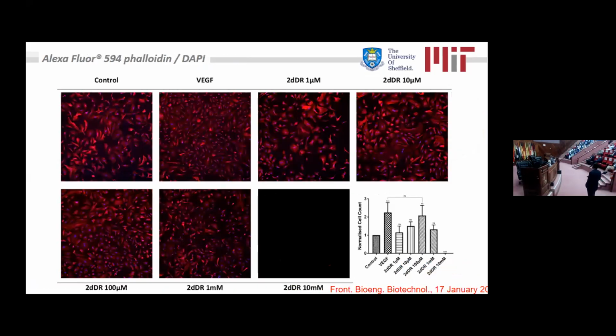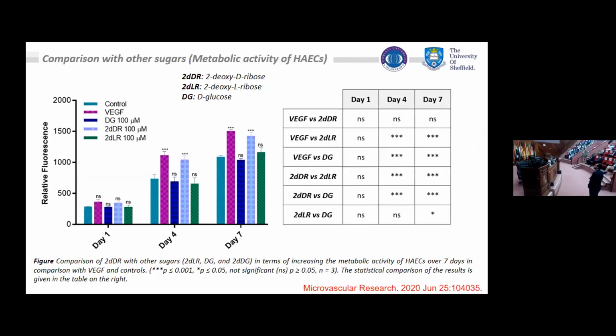So we compared this metabolic activity with the number of cells, and we found it consistent, that the 100 micromolar concentration was equally good like VEGF. And here, we compared with other sugars to see how they would do. What we found is that on day 4, 2-deoxy-D-ribose at 100 micromolar was equally good like VEGF. And on day 7, again, 2-deoxy-D-ribose was good. But the other sugars, like 2-deoxy-L-ribose and D-glucose, were not effective. We saw no significant difference between the control and these sugars.